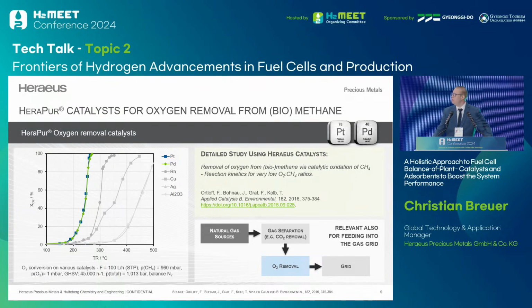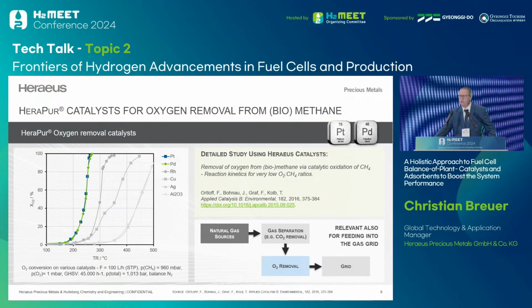There's a nice example here for oxygen removal. If, for example, you have a biogas, you can have traces of oxygen in this gas. And if you would go with this into a reformer, a pre-reformer, this is something this downstream component doesn't like at all, especially if you're using a nickel reformer catalyst. So, to protect this, ahead of this we use oxygen removal catalysts that basically oxidize, react with the hydrocarbons.